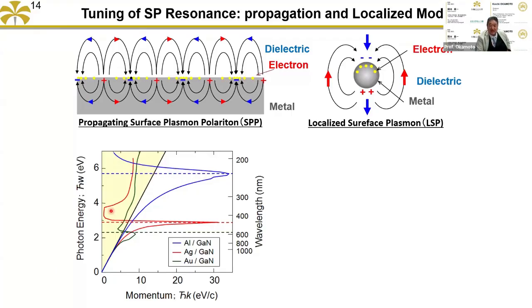But using aluminum, the peak is in the deep UV region, in the silver case it's blue, and in the gold case it's red. To tune that peak was difficult. But you can control the momentum, and then the matching condition was controllable. That's why momentum is tunable, and by using this method, almost 100% coupling is available.